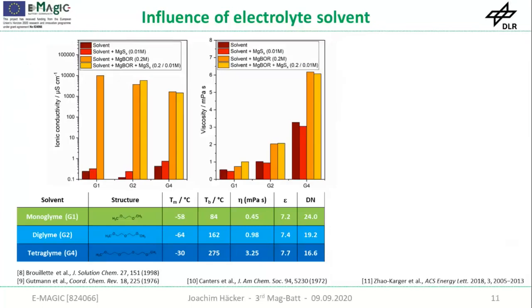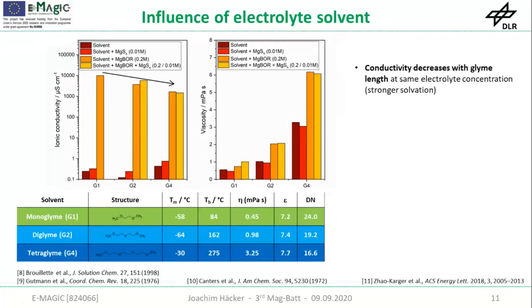To have a deeper insight, we synthesized some solutions and investigated the conductivity and viscosity. You have here the pure solvent, the solvent with polysulfide solution, then the electrolyte solution, and the electrolyte with the polysulfide solution. And you can see that the conductivity decreases with glyme length, which is for the same reason I mentioned before. So the stronger solvation of the cations with longer glymes. So tetraglyme increases the solvation of the magnesium cation